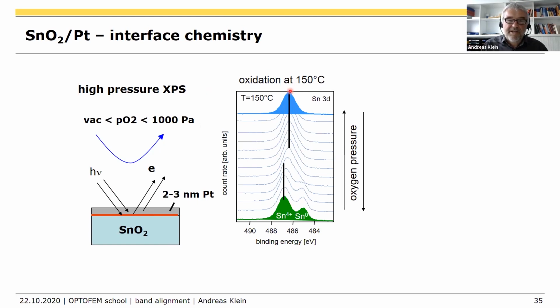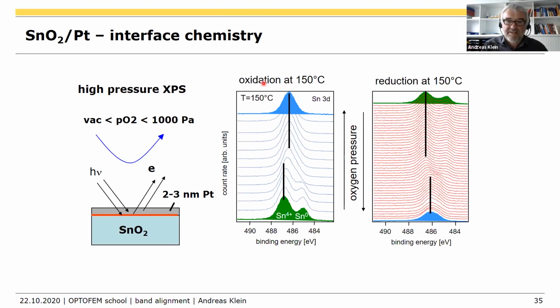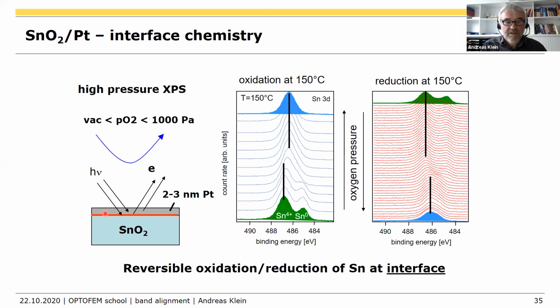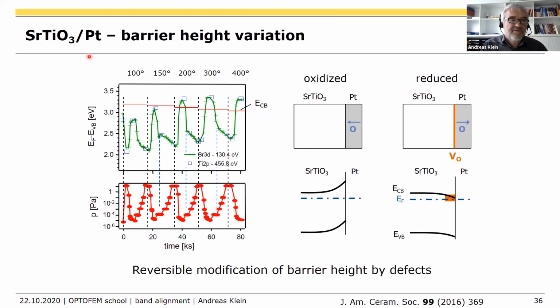Now we take the sample here and we simply remove the oxygen by pumping the vacuum. We do nothing else. And what you see, okay, we start here again, and you see the metallic tin is reappearing. And again, the Schottky barrier is changing. So that means somehow the oxygen is diffusing through the interface and is oxidizing and reducing the interface and thereby changing the Schottky barrier. We can do the same thing with strontium titanate and platinum. Same experiment, you see it's going up and down depending on the oxygen partial pressure.